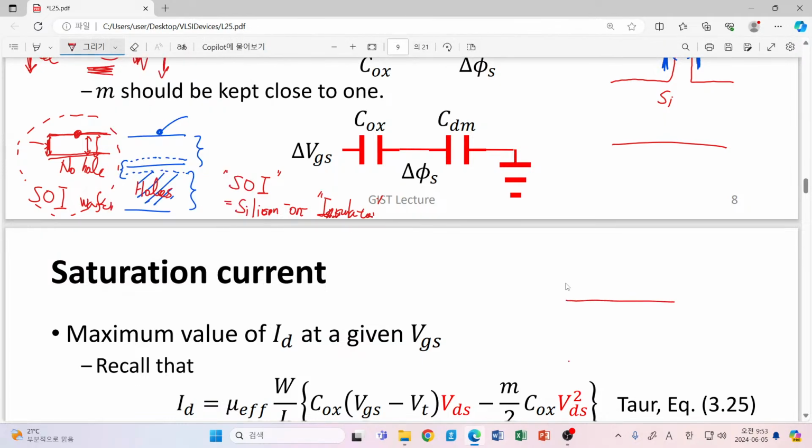Starting from a certain silicon layer, we introduce a different material. This one is not silicon, but a little bit different, very thin, just a few nanometers. After that, we can grow once again silicon, then the alternative material, and silicon.